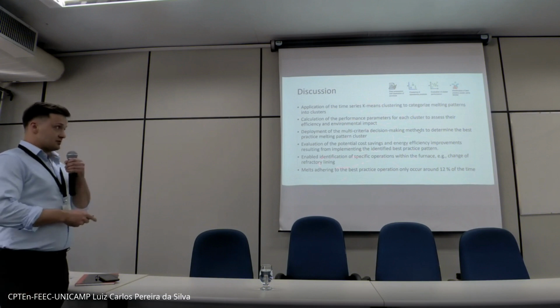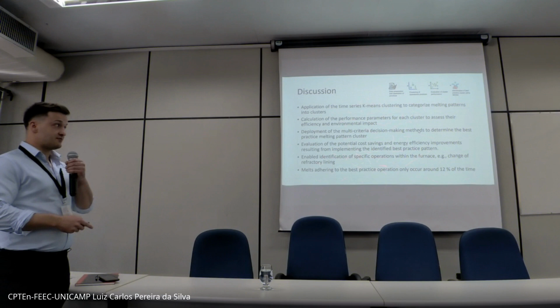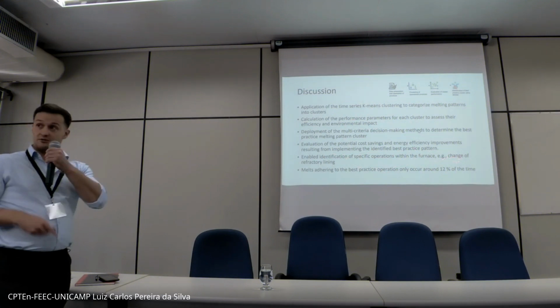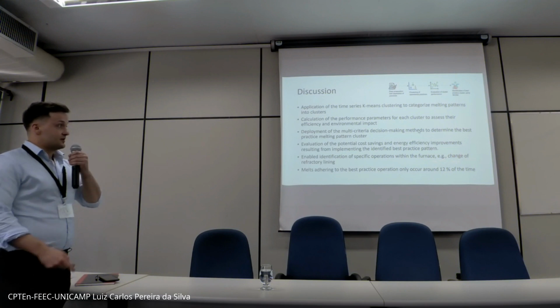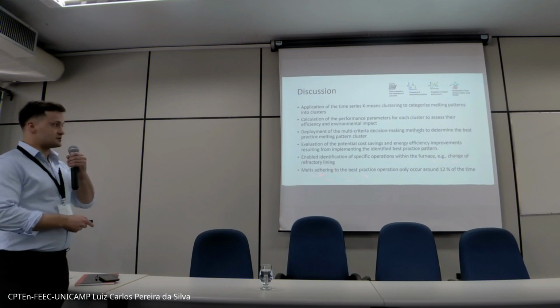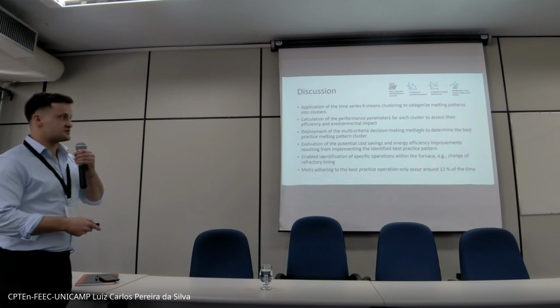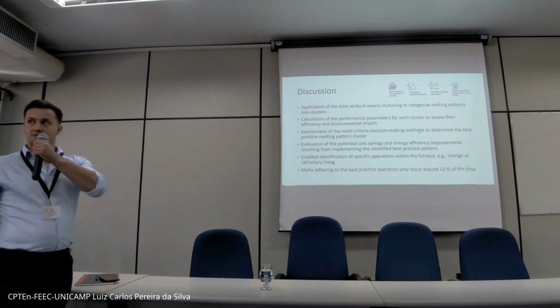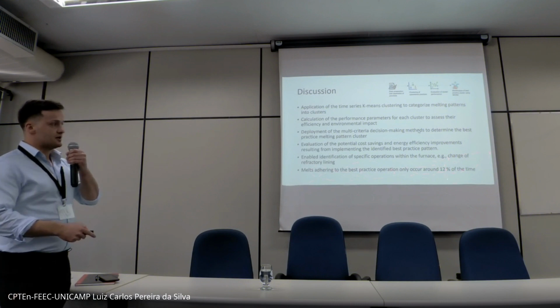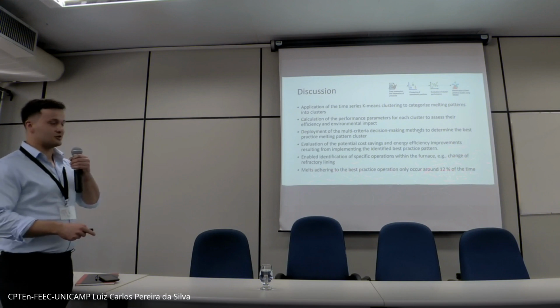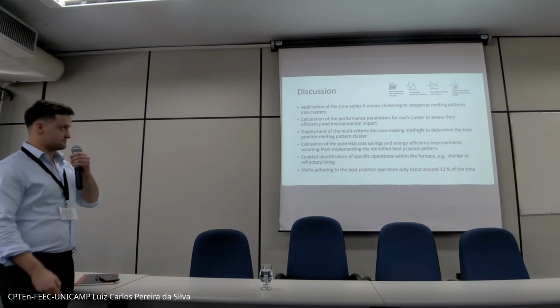This also enabled, as I said, identification of specific operations within the furnace, for example, the change of refractory lining in the furnace. And we also found that the melts adhering to what is considered best practice at the moment are only 12% of the time. So there's definitely potential for them to increase the number of times that they are doing best practice operation.